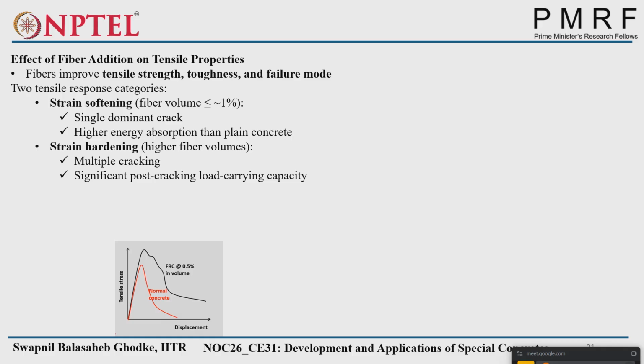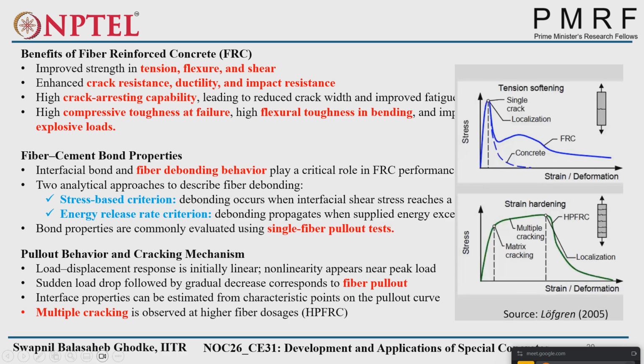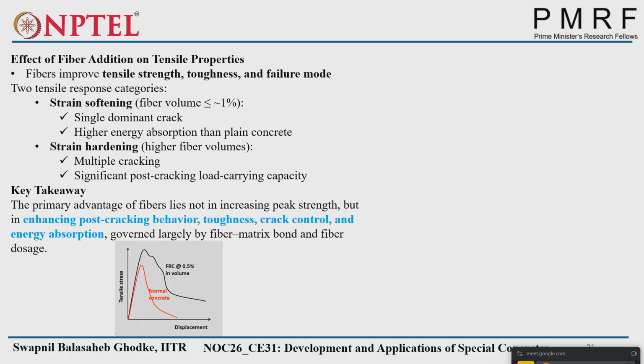Normal concrete will not show any strain softening or strain hardening behavior. It will directly go down, the curve we saw here. This is the strain softening behavior actually. Strain hardening means the graph will go up like this. We'll see the next graphs. So what is the key takeaway from here? The primary advantage of fiber lies not in increasing the peak strength, but in enhancing post-cracking behavior, toughness, crack control, and energy absorption, governed largely by fiber-matrix bond and fiber dosage.